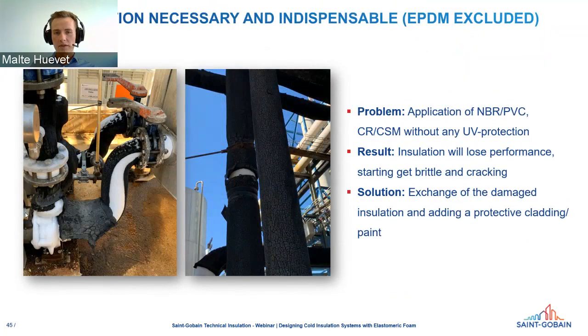This is a good example of how an insulation, if it's not EPDM, will look after 1 or 2 years in direct sunlight. The insulation itself will start to get completely brittle and fall into several pieces. In this case, we also have to exchange the whole insulation because its performance regarding thermal conductivity is no longer given. We need to completely re-insulate this system and also add, of course, at least after 1 day, a protective layer of paint or a protective cladding.